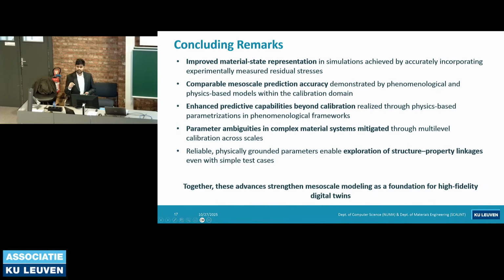But nowadays, they have an improvement in this strategy. They use a pencil beam and then characterize each voxel. In the older method, we used to get averaged-out data for the entire grain. But now, because of this new characterization method, we have data for individual voxels. So I think that would improve, and I'll be working on that data set in the coming months. Is that ID11, or which beamline is that? Yeah, ID11. Okay, interesting.